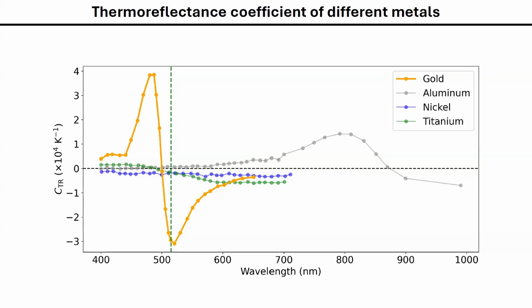I think the point would be, first of all, that on the bare substrate, you would have a worse coupling between gold and silicon oxide, and therefore lower transport towards your substrate. So probably this would also imply less sensitivity to heat transport across your flake. But yeah, we never explored experimentally what happens if we do this thickness dependence without the titanium additional layer. Okay.